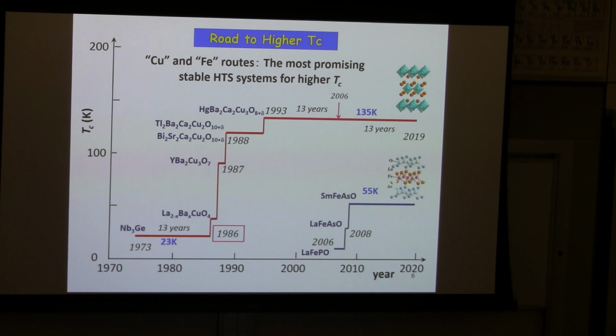So one way to search for higher TC is based upon these two distinctly high TC materials. One is copper oxide, cuprate. The other is the iron-based superconductors, which show a highest TC of 55 K at ambient pressure, of course. But unfortunately, even for this iron-based material, TC stopped rising right after the discovery of this material, so 55 K is still the record TC value for the iron-based superconductors.